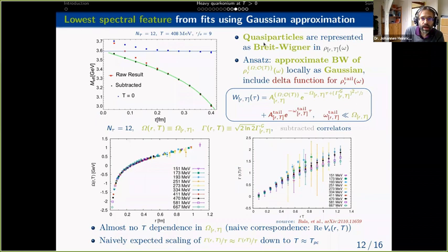So now we analyze these effective masses, or these first cumulants, in terms of a fit where we approximate the Breit-Wigner that would correspond to a quasi-particle locally by a Gaussian, which regulates the Breit-Wigner without needing too many parameters, and then add a delta function for this infrared tail. So this is the fit form. Here you see a result. In black you see these UV subtracted results for the finite temperature effective mass.